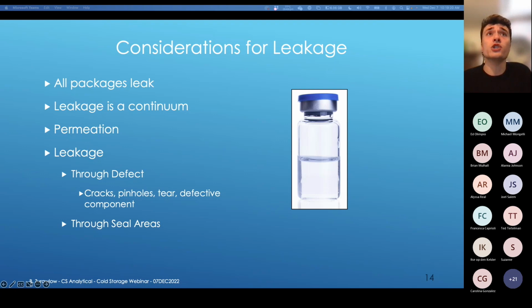And so when we consider leakage in general, it's well established that every package is going to leak to some extent. Leakage is a continuum, and so to say that it leaks or does not leak is one thing, but it's also at what leak rate or how intense is that leakage that we're seeing, and that goes back to the maximum allowable leakage limit. Permeation is also something that can be relevant here, whereby it may not be directly leakage. However, permeation is also going to have an impact, for example, on the headspace content of a package system. Ultimately, the drug product is not going to care whether that oxygen came from a leak pathway or from permeation if that product is oxygen sensitive.